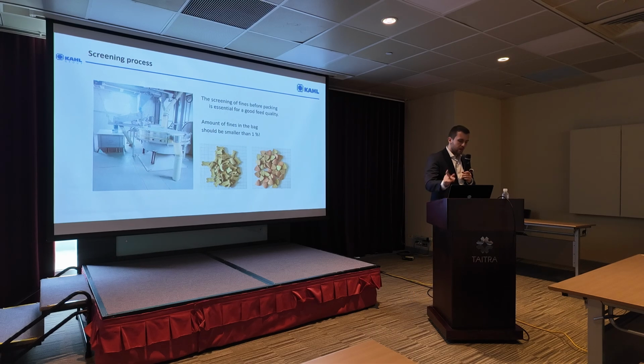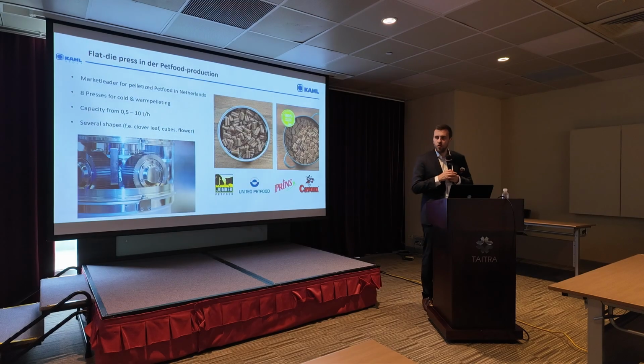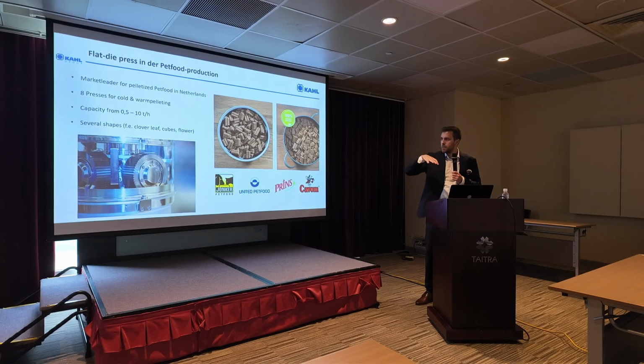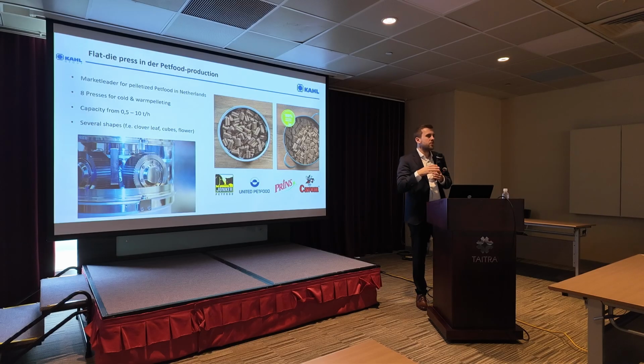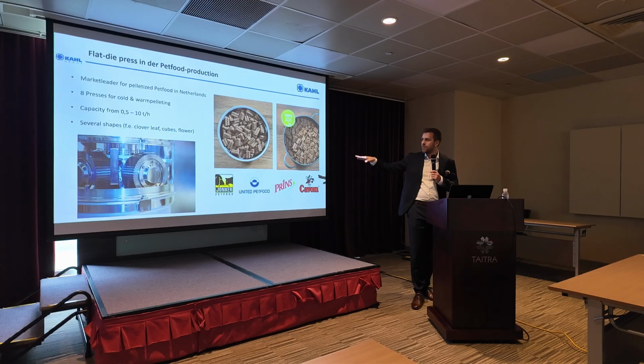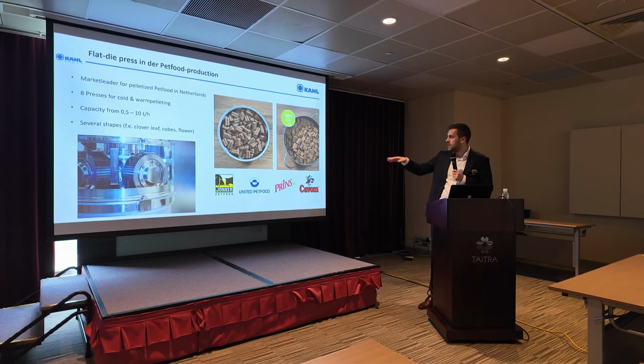As mentioned earlier, Amandus Kahl is well known for the flat die pelleting mills. So I also just want to give you a brief introduction to the pellet mill. Basically we have a pelleting chamber with rotating rollers onto a die. So not an extrusion die, where you have the die set up vertically and push the material with a screw against it. Here we have the roller rolling onto the die, pushing the material from the top through the die holes and then into the knives underneath, and then we get the pellets.